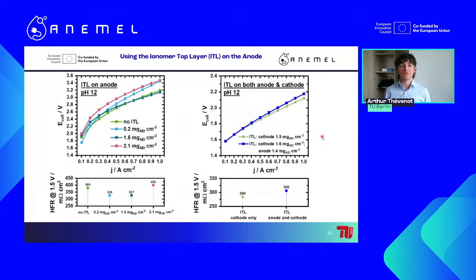So we wanted to have a little trial of the ITL on the anode as well. We first need to know that we already have some ionomer inside the catalyst layer of the anode for the binding properties. Of course, it will also enhance the OH minus transport, even though that was not the main purpose of it. But when we apply this ITL on the anode, and therefore no ionomer on the cathode at all, we see maybe a slight increase after putting a certain amount of ionomer, which is actually a bit surprising for us, as we saw that we had a way worse performance when applying a bit less and then having it directly better afterwards. So it was a bit surprising to us to see this trend. However, we saw that there was barely any improvement at all in that regard.